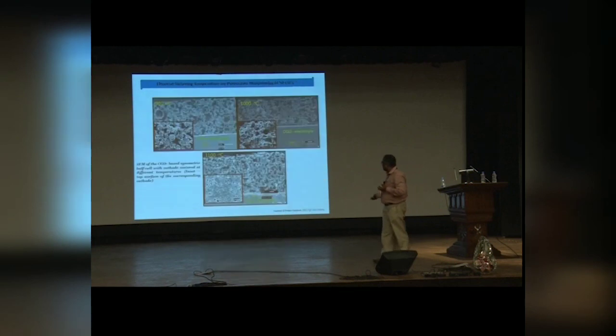again cells. But what I want to show you here is that although we have these types of buckyball structures in the powder form, after sintering at around 1100 degrees centigrade or so, we checked whether we are losing this particular morphology or not. If you lose it, then you cannot use it. Yeah. So here you can see that this type of structure is very, very important. You can see from 900, 1000 and 1100, the structure is collapsing here. As you can see in this case, you can retain that structure. So we need this type of structure. So this is one example of how microstructure plays a very, very important role.